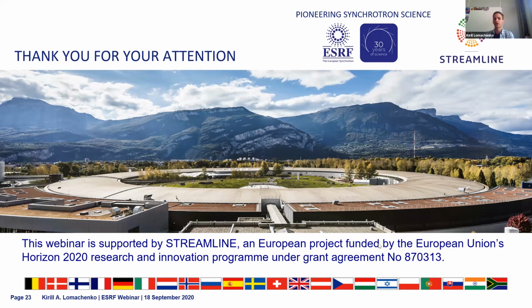You will have to use a fluorescence mode. There are different ways of measuring XAS - you can measure in transmission or in fluorescence. In transmission, I'm sure you will not get anything because you have too little iron. But for fluorescence, I think there is a chance to get XANES for sure, and depending on how much time you are ready to invest, if you measure for a long time you can get also some reasonable quality EXAFS. But again, it depends on your scientific question. If you want to determine the iron oxidation state, for example, then XANES would be enough and is surely perfectly feasible. If you want to determine very fine details of local structure 5 angstroms away from the iron atom, then no. So it depends on the composition and on the questions you want to answer. The general answer is that it's most probably feasible.